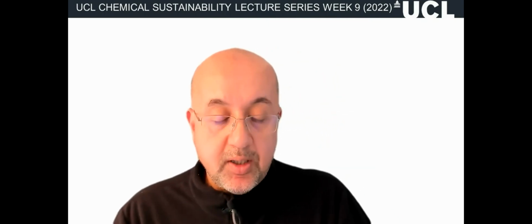Well, I don't think it's electroactive at all, unless it's highly distorted. And so zirconia doping seems to stop that degradation pathway, that transformation of structure to rock salt. So there is a bit of literature on it. It's not electroactive, and so it has that effect. Now, why that amount of zirconia is optimum, I don't really know.